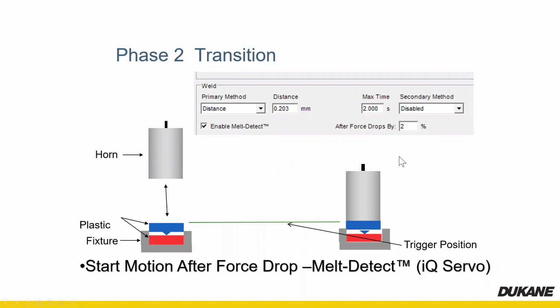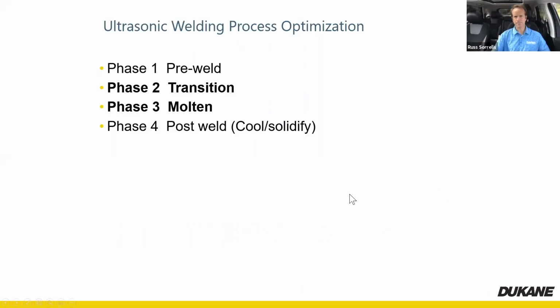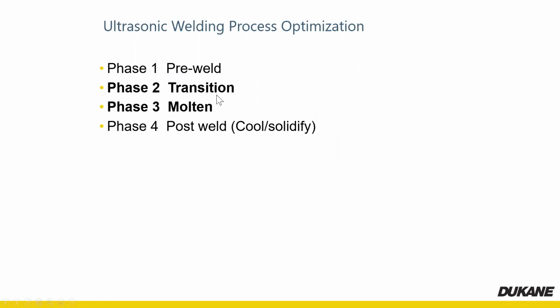Basically we know that the plastic is melted because the force has dropped, because the only reason for that force to drop is because the floor dropped out from under it. So we've got everything under compression. We've got ultrasound turning on. When ultrasound turns on, you typically see a little bit of an increase in force. And the only reason for that force to drop at all is because the plastic has started melting. Okay. Makes sense.